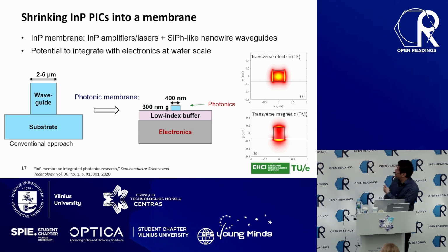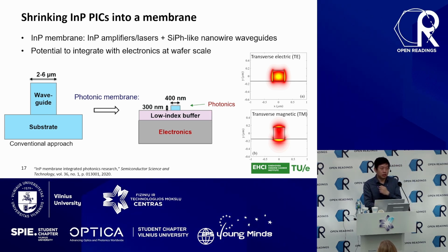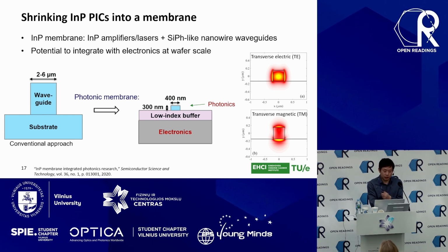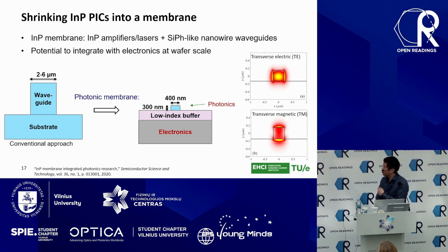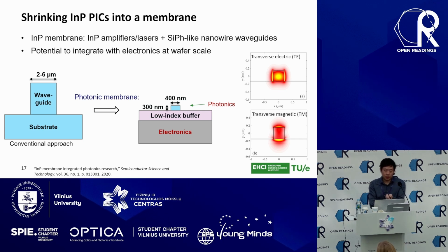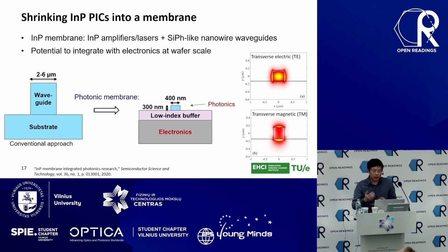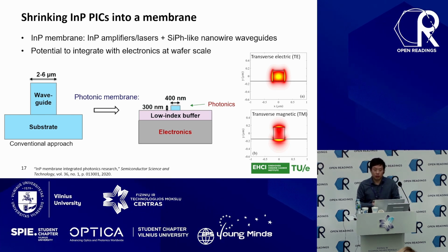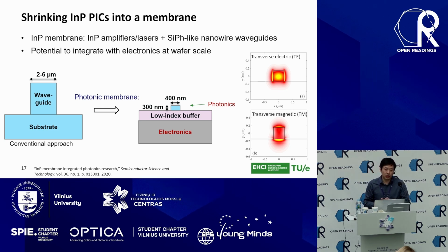On the right, you can see a typical mode profile, and you can see that the optical mode is very tightly confined in these indium phosphide waveguides. And also, as I already gave a hint here, because now my optical system is independent of the substrate, I can integrate this system onto any substrate I want. For example, an electronics substrate, right? So it can also potentially enable an integration with electronics at wafer scale.